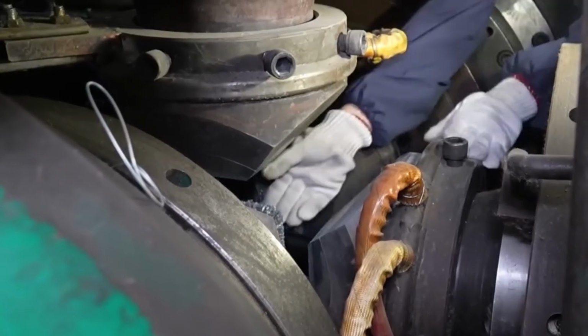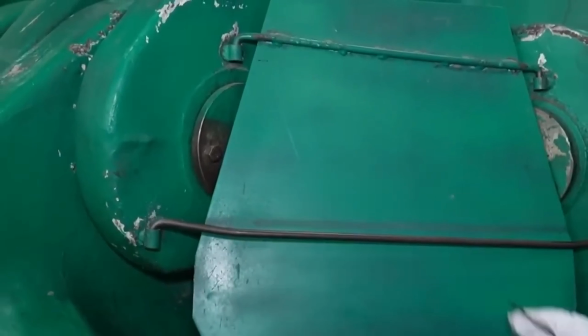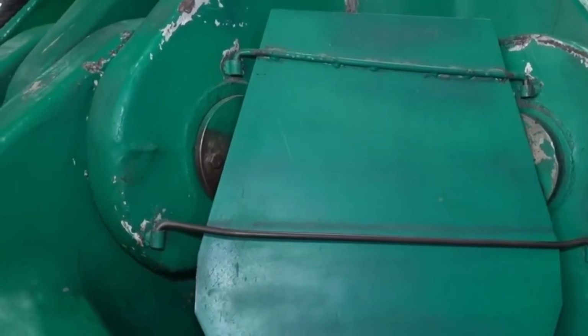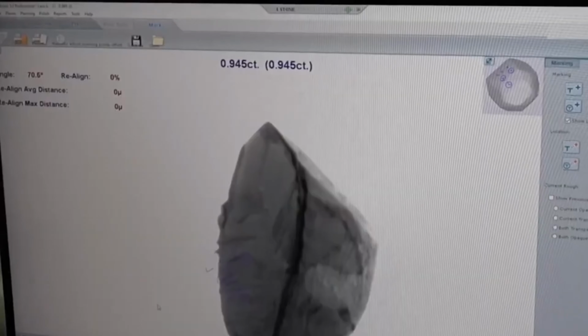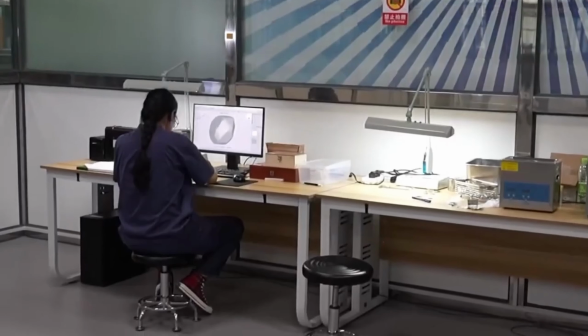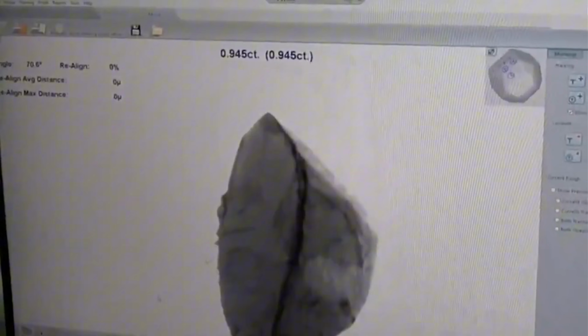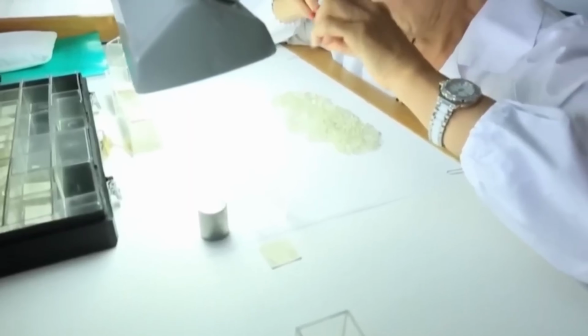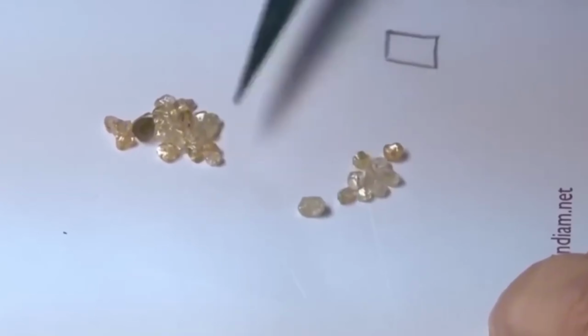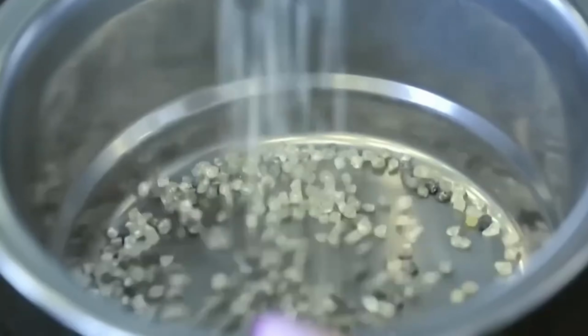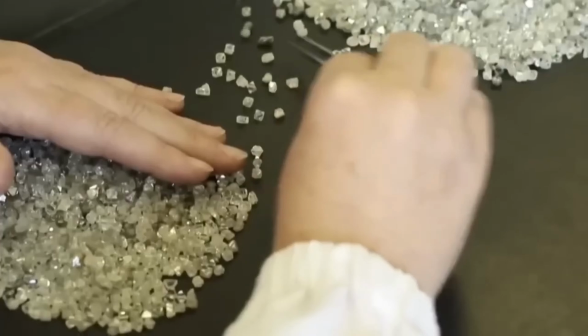If any variable drifts, the growing surface can become cloudy or structurally distorted. A CVD diamond typically grows at a rate of 1 millimeter every few days. Large stones may take weeks. During growth, engineers check the crystal with optical sensors, laser scanners, and spectroscopy tools that detect impurities in structural alignment. If nitrogen or boron atoms enter the chamber, the diamond may grow with unwanted color. Many high-end producers therefore use gas purification systems that strip contaminants down to parts per billion. When the diamond reaches the desired size, the plasma is switched off, the chamber cools, and the newly grown rough